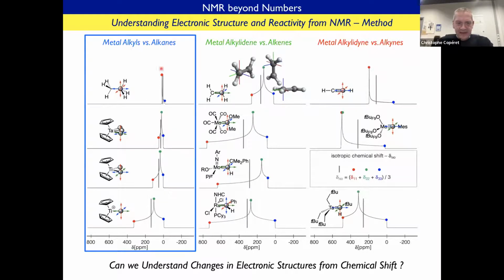And in fact, what you can see is that this is true for most compounds. But when you start to have this cationic metal-carbon bond, you have another anisotropy which is very close to what you see in an alkylidene. And what is very interesting as an organometallic chemist is that these compounds are very well known to be highly efficient olefin polymerization catalysts, while all these other compounds are not able to do olefin polymerization. So obviously the question I can ask is, is there a relation between this anisotropy and the reactivity of these compounds?